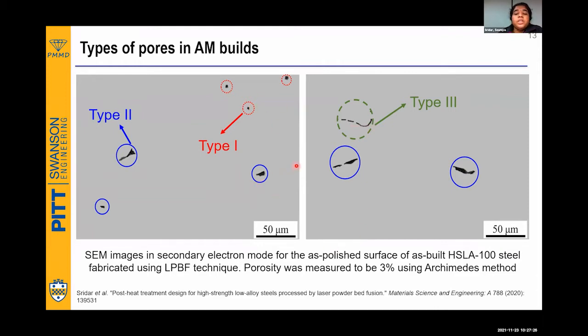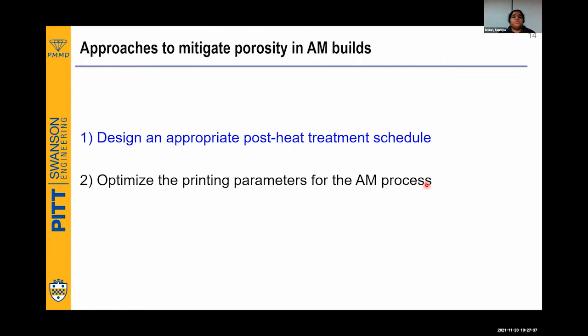Okay. Now the porosity measured for this build using the Archimedes method is around 3%, which is an alarmingly high porosity. Okay. So what are all the ways to mitigate porosity in a porous AM build? So what if a build becomes a failure, we need not always throw it out, because we have spent a lot of energy, and they even charge us for doing additive manufacturing builds here. So there are two ways to mitigate. One is to design an appropriate post heat treatment schedule, and the second one is to optimize the printing parameters.